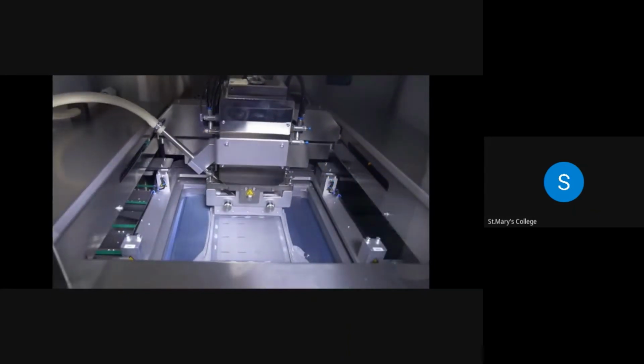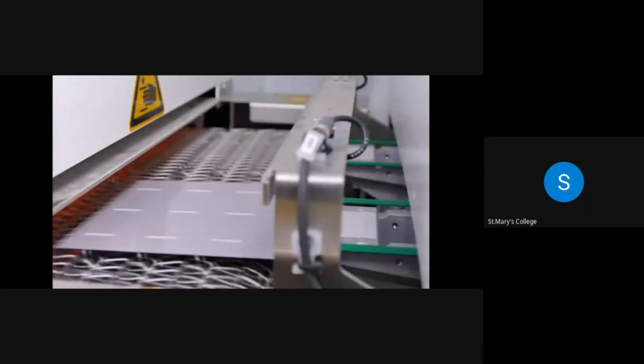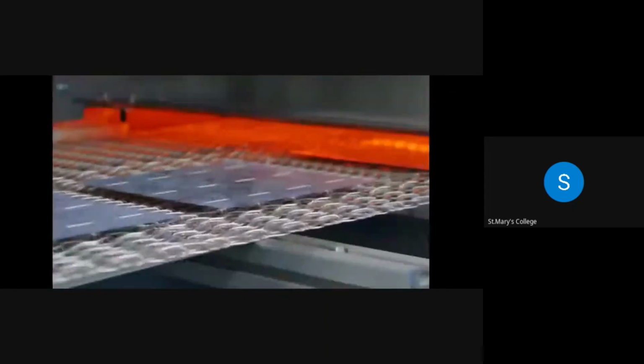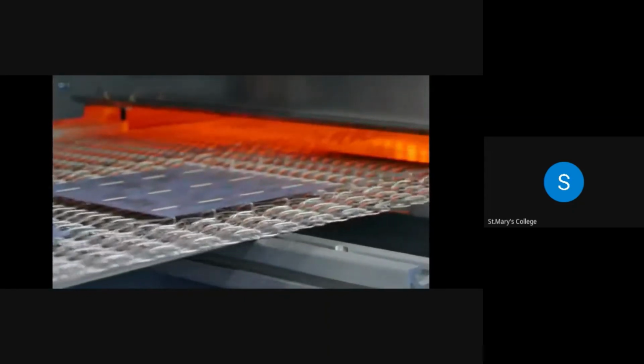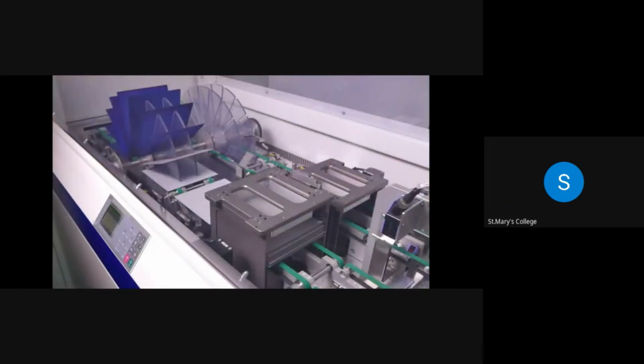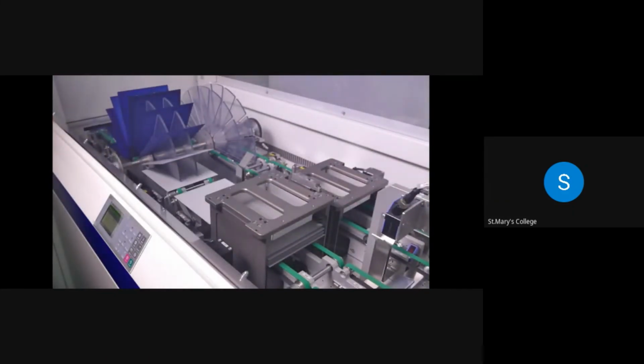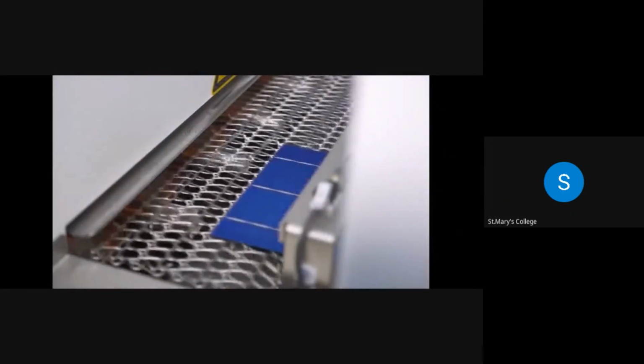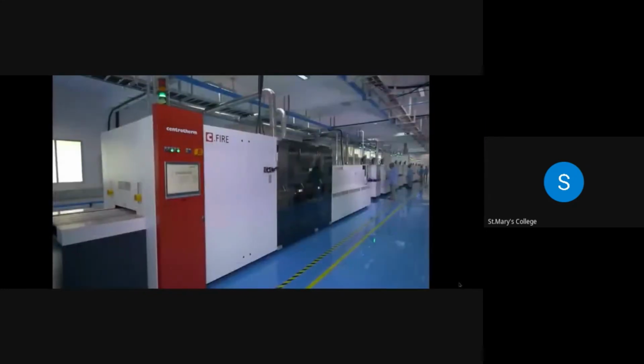bus bars. CCD cameras are used for wafer position detection and alignment. Separate printers for front grid lines and bus bars ensures high aspect ratio screen printing and hence higher efficiency. Screen printed wafers are dried and sintered in an infrared belt contact firing furnace where a sharp temperature profile is maintained to ensure contact adhesion. Finished solar cells come out of the firing furnace.